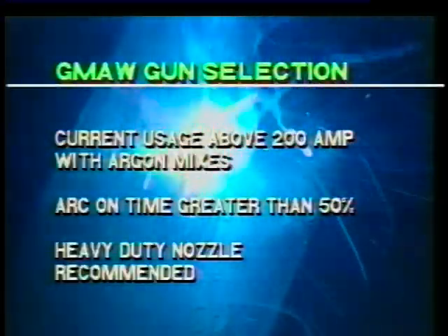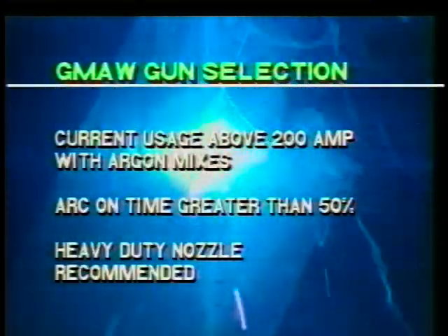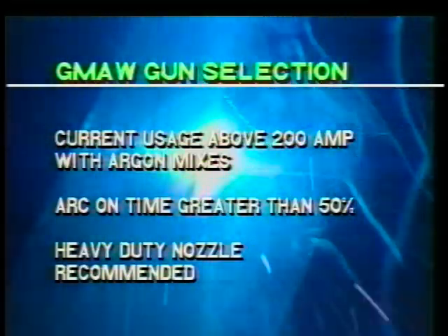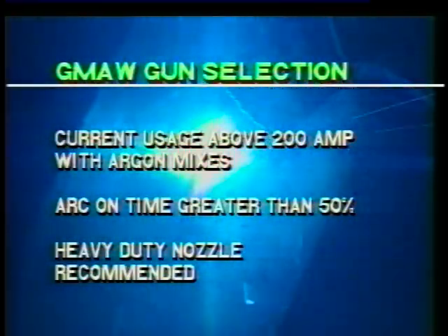When using argon mixes above 200 amps and arc on time greater than 50%, to extend the nozzle life, use a heavy-duty gas nozzle.